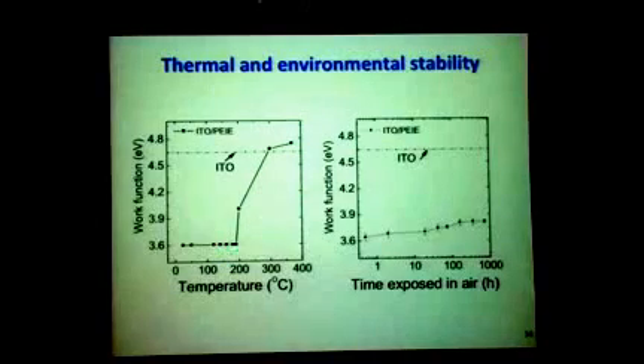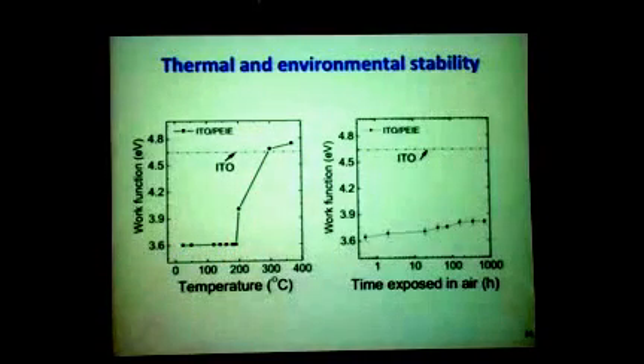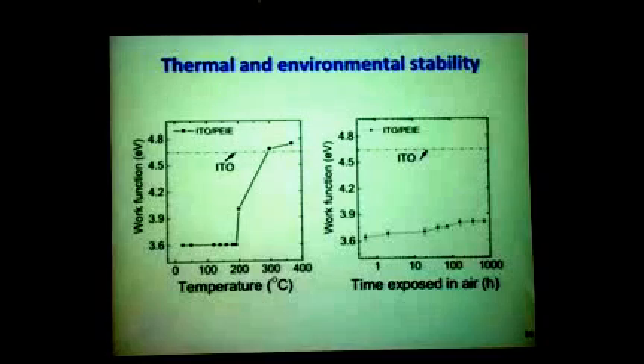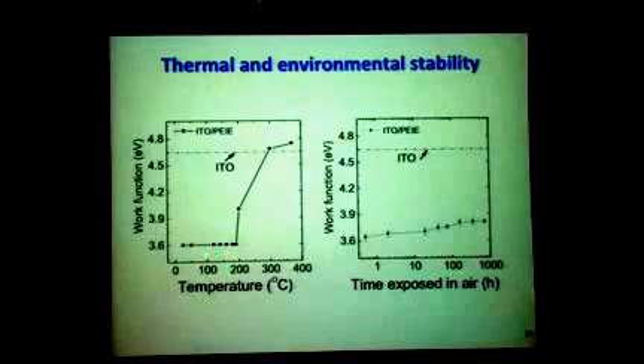These materials are actually fairly stable up to 200 degrees C, which usually gives you enough flexibility to work with plastic substrates. Typically, a lot of these process temperatures never exceed 150 degrees C.